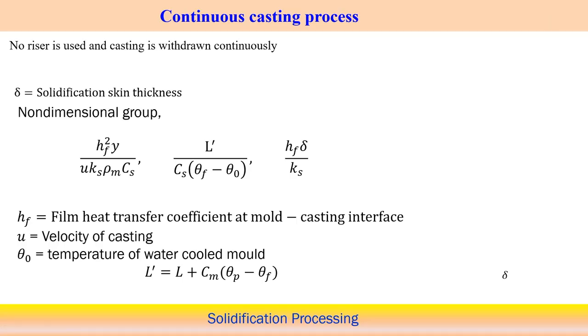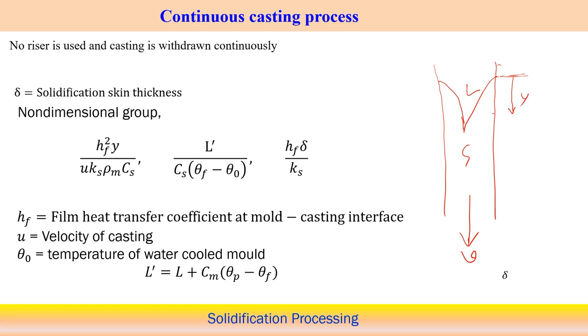Of course, the continuous casting process to some extent is also similar, as we can utilize a high copper mold, and even a water cooled copper mold is usually utilized in the continuous casting process. But it is not directly correlated; in continuous casting the solidification time is difficult, and the problem is somehow different in this case. So, here what we can see in the continuous casting process, how it works, is that the molten metal is poured from the top surface, and then tries to solidify; this is the liquid metal and this is solidified, and with a certain velocity the solidified strip comes out. Now, it depends on the distance y.